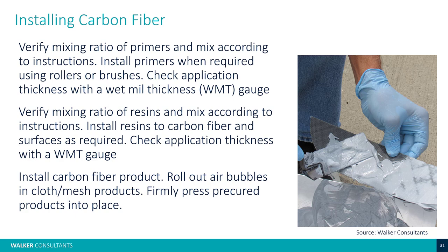And then check the wet mil thickness. The biggest part of this that I want you guys to know is to check your wet mil thicknesses in the field. You don't want too little, because then the product may not bond as well. You don't want too much, because then you're wasting product, and you might not get a decent bond either. So you've got to be in that happy zone, just about perfect to where the manufacturer wants it.